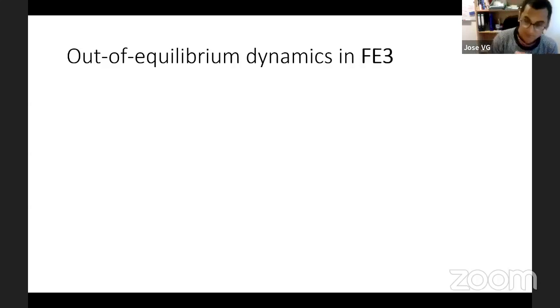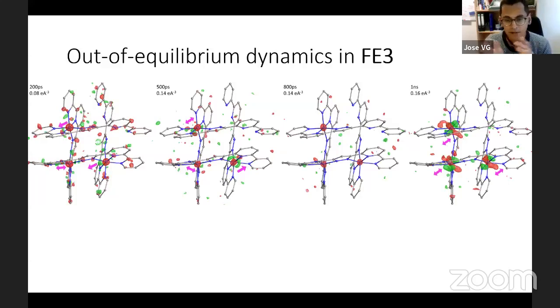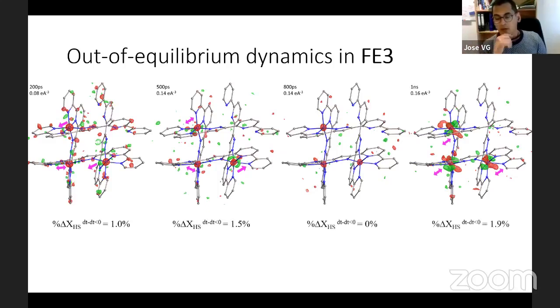What has changed since last time is that we have published what happens in the iron 3 grid. In the iron 3 grid, we observe something similar. There is some structural rearrangement over time. And of course, we also see that this structural rearrangement stops at 800 picoseconds because the light-induced step finishes at 800 picoseconds, and after that, at 1 nanosecond, the elastic step also takes place. It's very similar to what happened in the iron 4 grid.